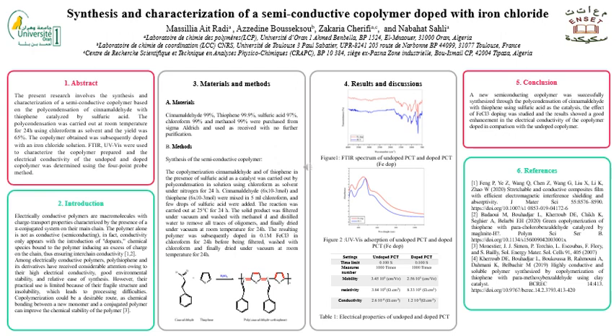The polycondensation was carried out at room temperature for 24 hours using chloroform as the solvent, and the yield of the reaction was approximately 65%. The copolymer obtained was subsequently doped by an iron chloride solution for 24 hours. Infrared spectroscopy and UV visible were used to characterize the copolymers prepared, and the electrical conductivity was determined using the 4-point probe method.